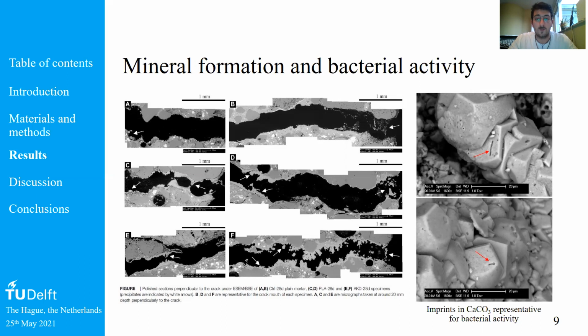While for both PLA, which is the one in the middle, and AKD, that is the one at the bottom, you see that precipitates growing at the sides of the crack are way more than those that we can see in the crack related to the plain mortar. So that is also confirming the ability, or let's say the compatibility, of our healing agents with self-healing mortar. And also on the right, we see indeed calcium carbonate crystals that have bacterial imprints that are representative, according to the literature, for bacterial activity in our matrix.